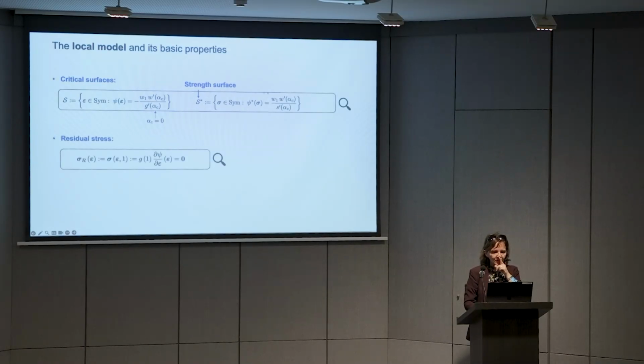But there's also, so this is very important for nucleation, because you want to be able to have a strength surface of a desired shape, and also of a desired size. On this strength surface you will read your tensile strength, your compressive strength, your shear strength, and you will be able to study nucleation on this surface. But then there's the other side of the medal. The other side of the medal is what happens when you have a fully developed damage.